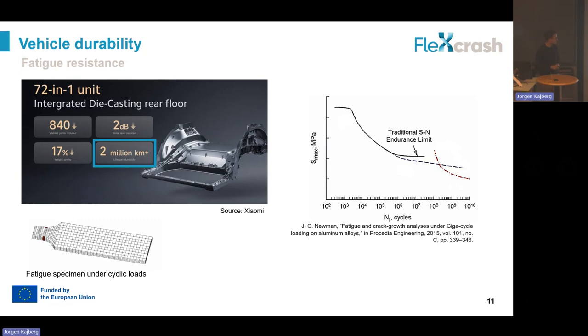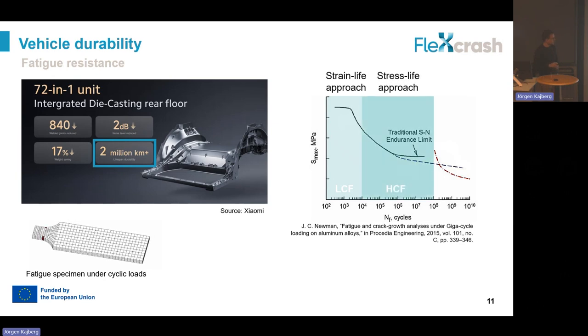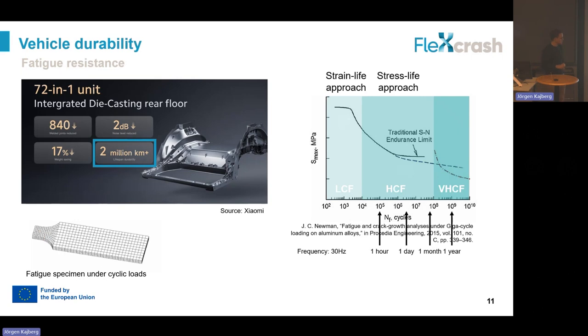The most known strategy is to use the SN curve, where we have different approaches: the strain life approach, where we have huge stresses; the stress life approach, the common one, I would say, and the most proper to characterize the fatigue limit related to millions of cycles. And then we have the very high cycle fatigue, that's another story. But the point is that if we want to get this SN curve for a given material, we need a lot of specimens, and also, as you can see here, a lot of time, since only one specimen in this regime of millions of cycles takes from days to months.